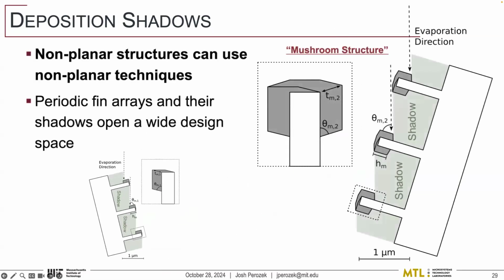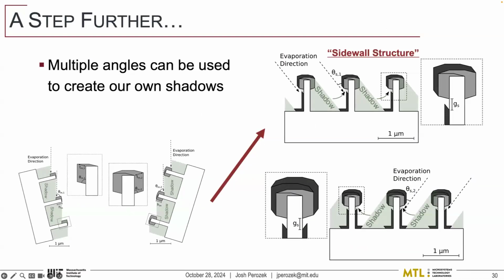So, you might imagine we can flip it on the other side. We can do a second deposition. We can keep our structures more symmetric. Where it gets a little more intense is if we now use the overhangs that we just created and make more shadows with them. So if we tilt it at a less extreme angle, the region underneath what we call the mushroom of a mushroom structure also forms a shadow. And we can keep using this to build up and eventually have a sidewall structure. So that's where we have metal along the sidewall of our fin here. And now it's starting to resemble a FinFET, but our actual devices are way more complex.